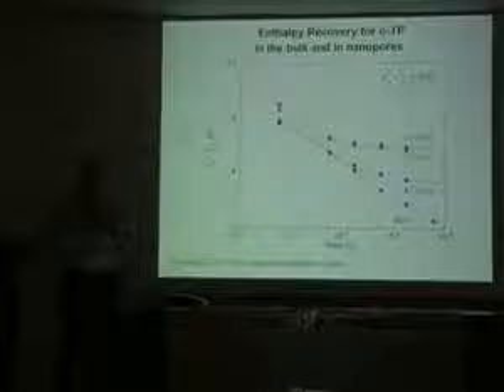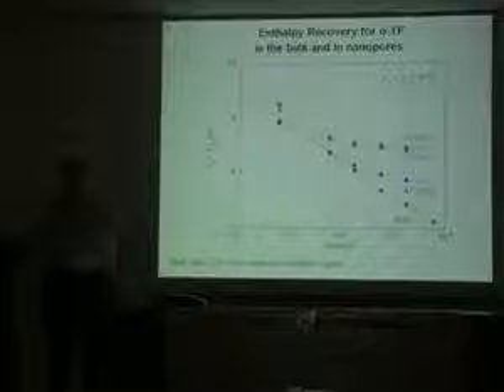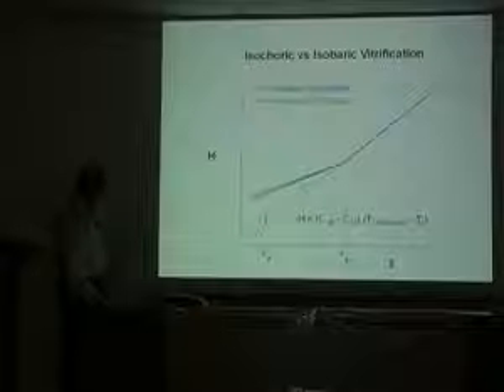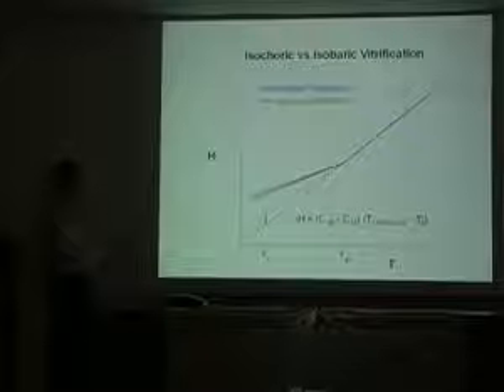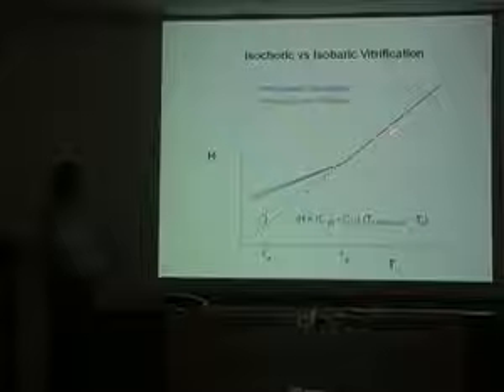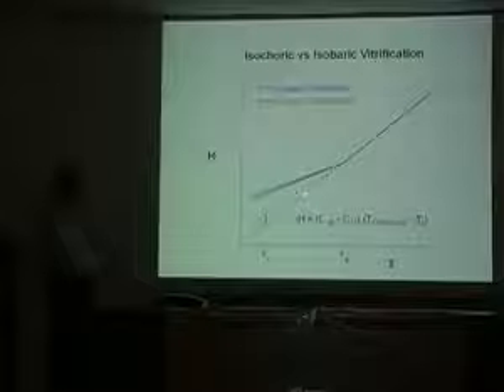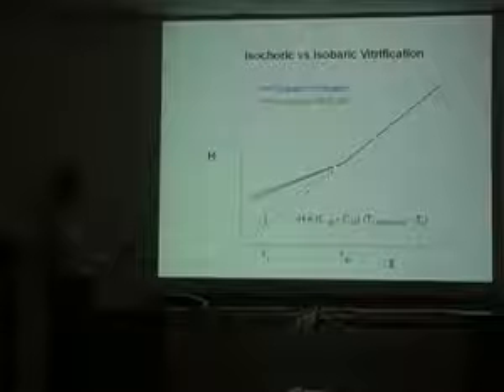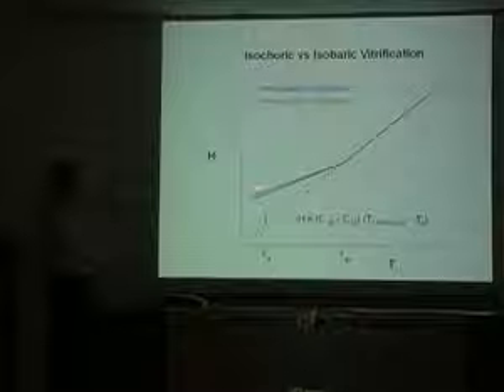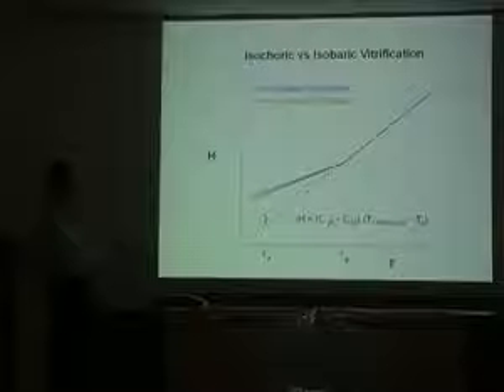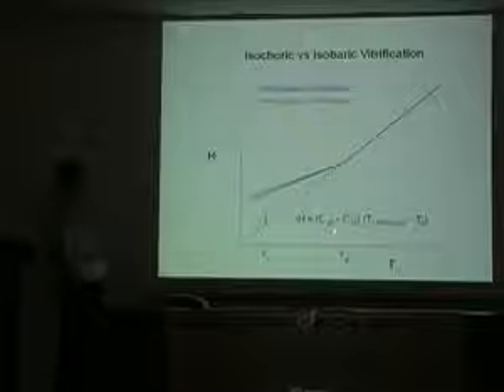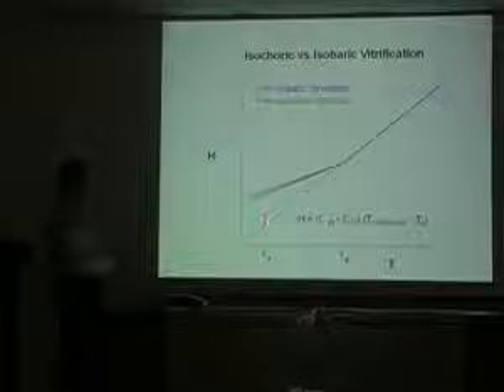Or is it occurring at, it turns out, in these experiments, the glass transition is also observed to be reduced in the nanopore. Okay, so you put the orthoterphenyl in the nanopore, and the TG goes down. So what we thought was, well, maybe if we have isobaric or isochoric behavior, we're going to have differences in enthalpy. So here's the equilibrium line for the isobaric condition. Here's the equilibrium line for the isochoric condition. And then this is what happens if we did the vitrification at the different points. Okay? So you have different enthalpies.